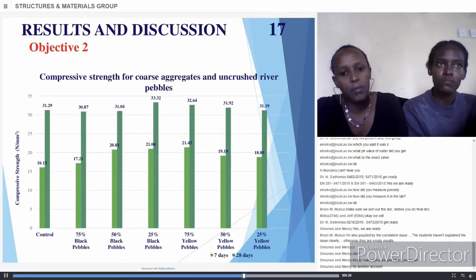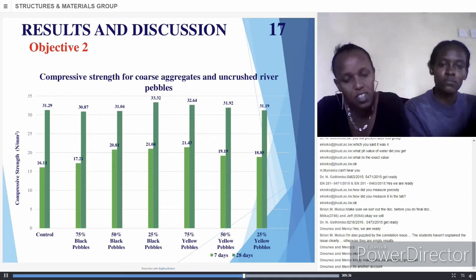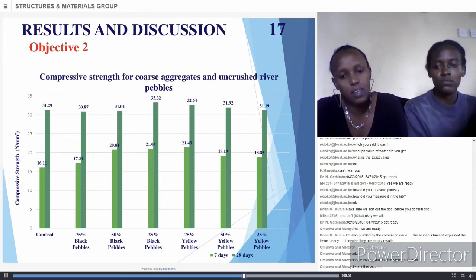For compressive strength, the strength for the black pebbles was reducing from the control, which had a compressive strength of 31. And if you look at the 25% river pebbles, it had the maximum compressive strength, and that's what we used for casting the beam. That is objective number 3: we cast the beam using the optimal mix.